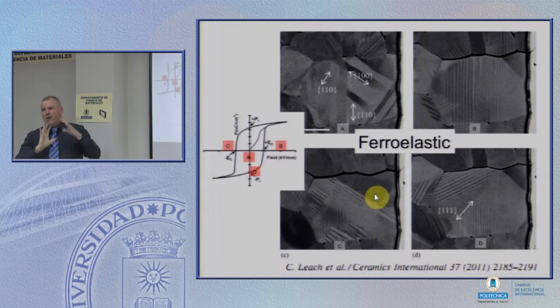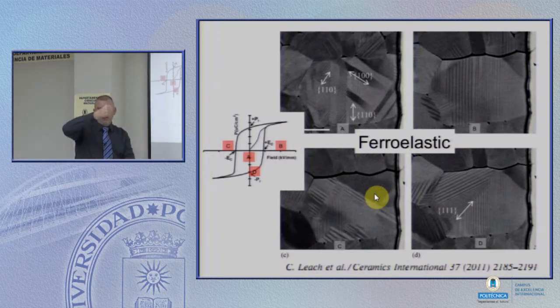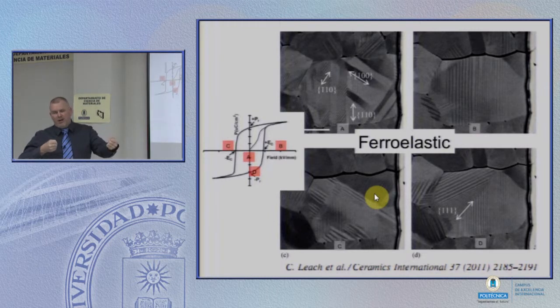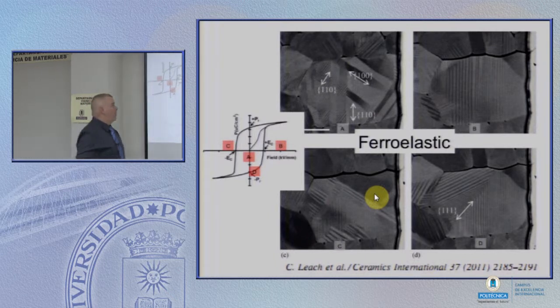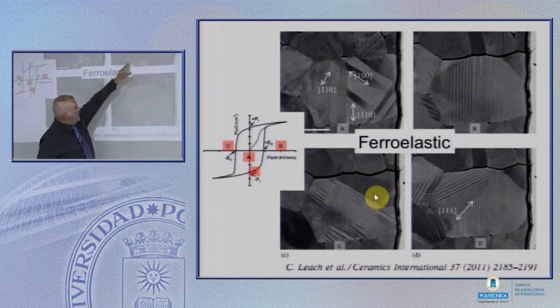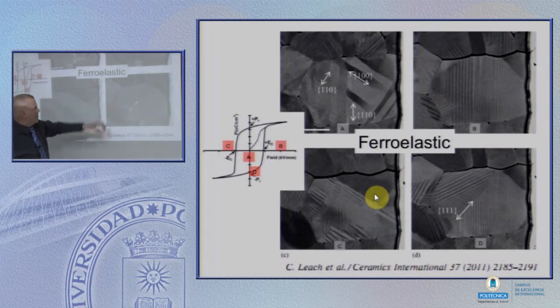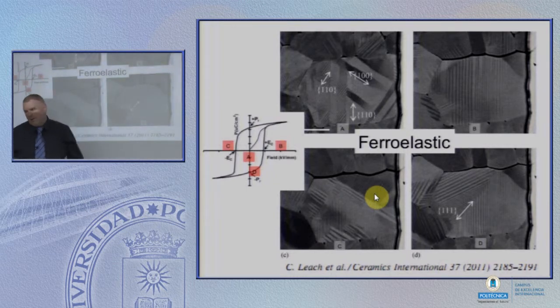Right? So we end up with about equal fractions of those possibilities. We have the long axis, any one of these three possibilities, and then within those we have the possibility that it's plus or minus. So essentially six possibilities that are viewed. Here, these are just showing the ferroelastic component, so the mechanical component, and you can tell by the imaging that it's going to be alternating points.